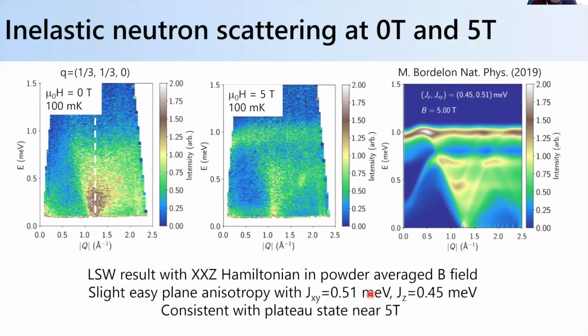It should say something. I agree that the fact that you have a sharp phase boundary is one of the things in my mind that's been an enduring mystery, right? Why do we have a sharp phase boundary in something where the G tensor is reasonably anisotropic? So the in-plane G tensor is roughly twice the out of plane. And yeah, it's a good question. It should tell us something about the quantum disordered ground state, the fact that it all wants to polarize at once, at least within this particular system.